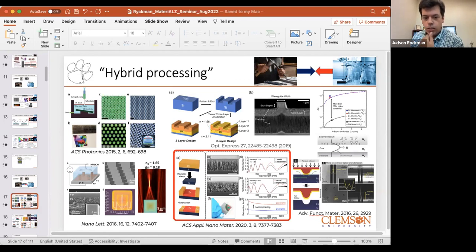So that's a really good question. If you want to apply a DC field, silicon, at least classically, doesn't have the Pockels effect, that electric field sensitivity, but there have been some demonstrations of a DC Kerr effect in special types of silicon that might be doped or have stress. So that could be possible. In our case, we haven't really studied that. But certainly the plasma dispersion effect would be there. If you change the charge carrier density, you'll have some index change.